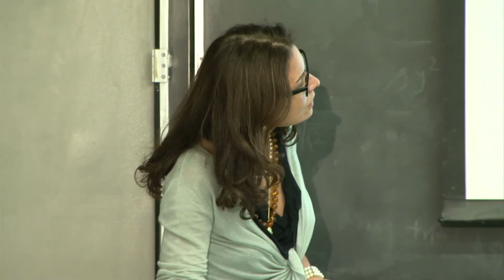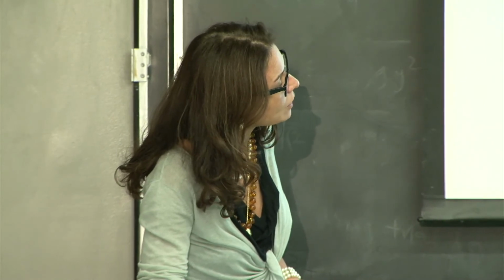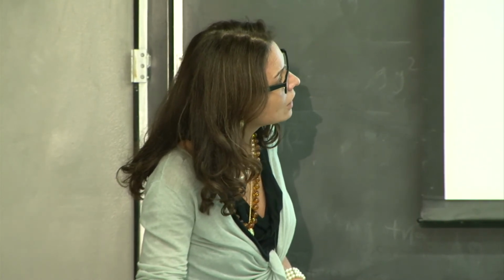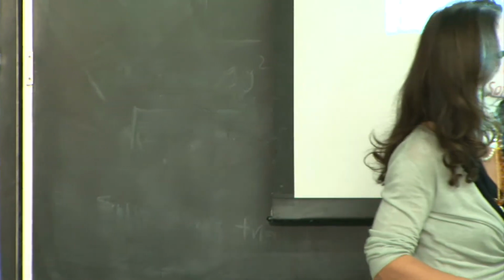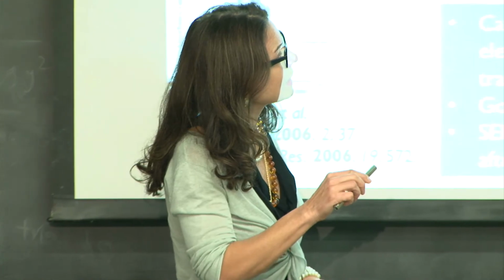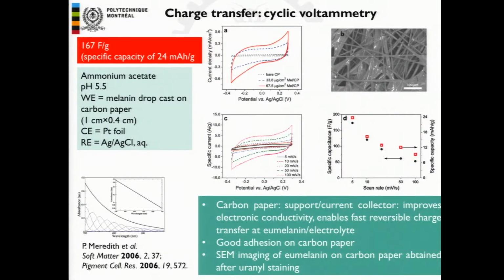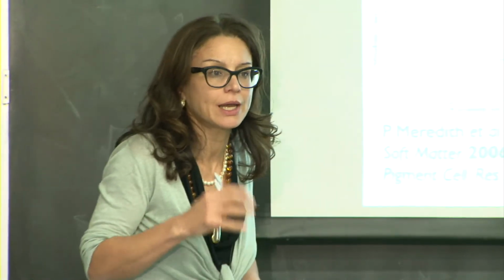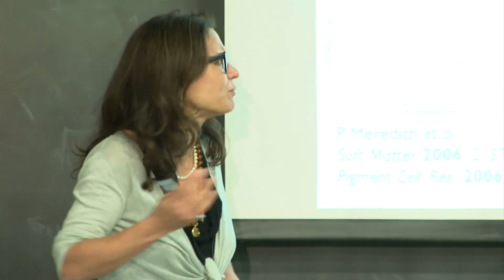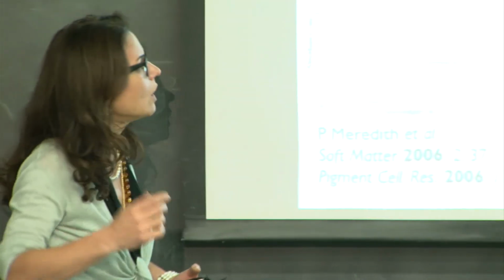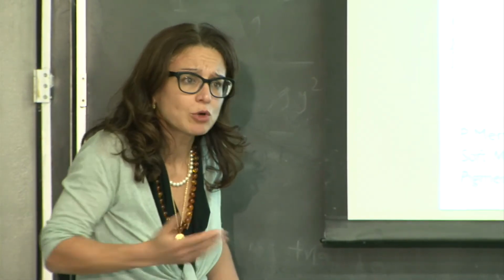And another element, apart from the development of a flexible micro-supercapacitor, that especially here I would like to raise. What you see in the scanning electron microscopy image are carbon fibers at the micrometric scale, and then here and there a few white clear spots. Actually, to image melanin on carbon current collectors, we had somehow to stain. Even in electron microscopy, you can stain. We did a few studies even here at McGill. Then I think we kept going on campus, but okay, there is a wonderful facility here too. So the point is that we had to stain because you want to reveal carbon on carbon.